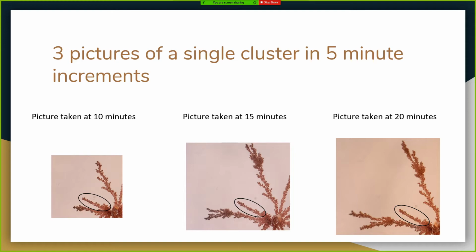This is nothing new. It's expected due to the larger branches shielding the shorter ones. This could happen for a number of reasons, including general blocking of the direction in which the copper ions from the solution can reach the branch, or potentially from local electric fields interfering with the shorter branch. Since the copper ions are conductive, the fractal is part of the ever-growing cathode, so there are all sorts of local electric fields that can be assumed to be happening.